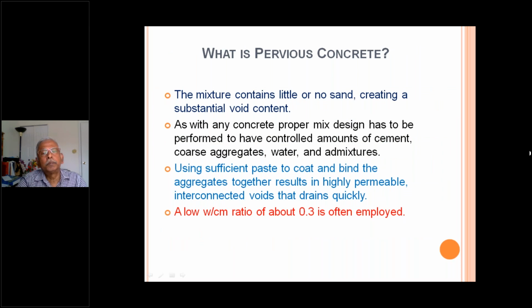Of course, let us see what is pervious concrete. Actually, it is a concrete with no sand, creating a substantial void content. Actually, not using sand also is advantageous in India because in many areas, sand is in short supply. As with any concrete, proper mix design has to be done so that we have enough void ratio. And using sufficient paste to coat and bind the aggregate is required, which results in highly permeable interconnected voids that drain quickly. A low water cement ratio of about 0.3 is often employed.